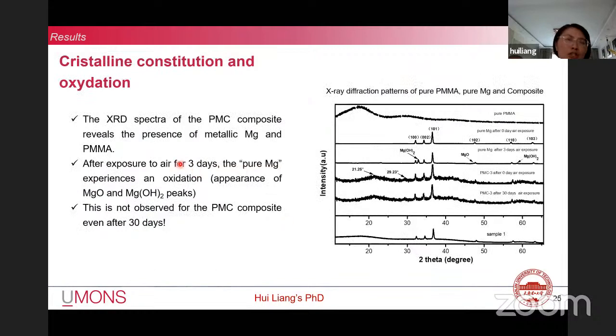And for the constitution and oxidation, refer to the XRD spectrum of PMC. We could find the composite PMC put in air for 30 days has no MgO and Mg hydroxide. But refer to the spectrum of pure Mg, put in air for 3 days, we could find strong diffraction peaks of MgO and Mg hydroxide. We also find the diameter of Mg in the composite is similar to the pure Mg.